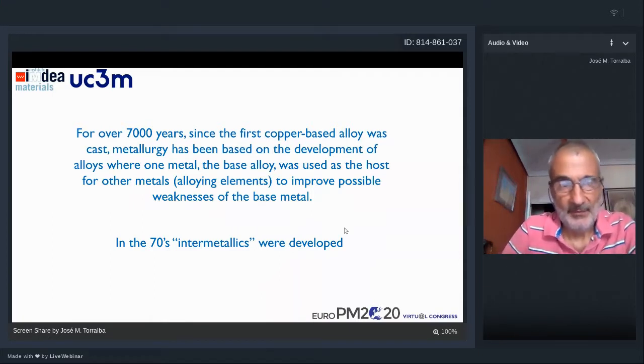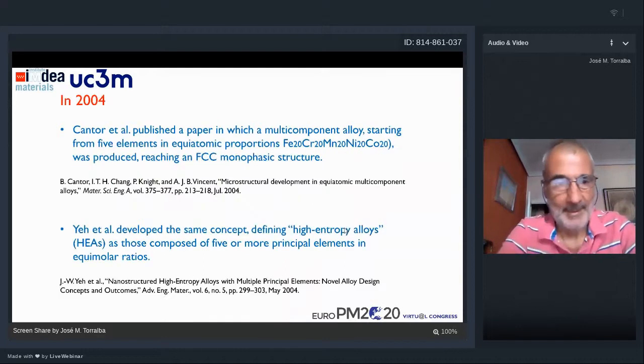But in 2004, there were two papers published, one by Cantor and collaborators, and the other one by Yeh and a collaborator, in which they developed a new concept of alloy. It is the concept of high entropy alloys. In this concept, they demonstrate that if you mix 5 elements in equiatomic proportions, you can have, in some conditions, one single phase. That means that you don't have, as could be expected, intermetallics, precipitates or different brittle phases inside the main structure.